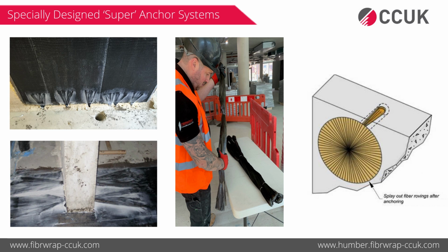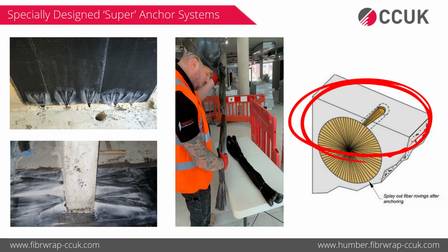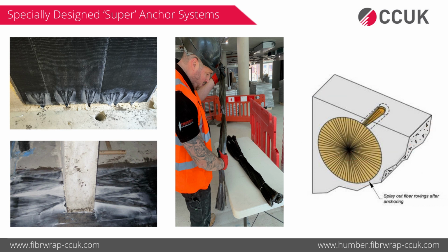And that's a small schematic on the right, yeah? Yeah, small one. So how it works is that we drill a hole into the concrete, we saturate the anchor, put half of that anchor into that drilled hole, which is filled with epoxy, splay the remaining half onto the face of the concrete, and then put one more layer on top of it. So now this will become one unit which will cure simultaneously, but it is actually going into concrete, so it provides you additional anchorage or bond capacity. So debonding or delamination failure will not happen.